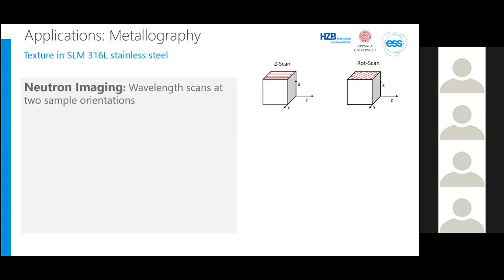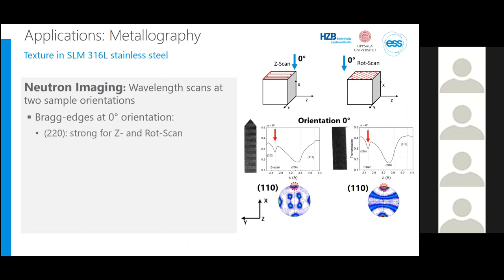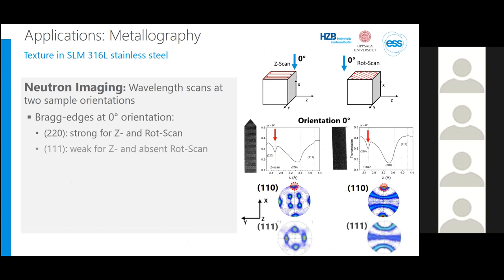What we then did was perform wavelength selective neutron imaging on these samples. The spectra for the samples oriented at what we term 0 degrees are what you see here. They show a strong 220 Bragg edge for the Z and the rotation scan. The 111 Bragg edge is rather weak for the Z scan and actually absent for the rotation scan. If you look at the pole figures on the bottom, you can see the corresponding pole indicated with a circle that is probed by the imaging in this orientation.